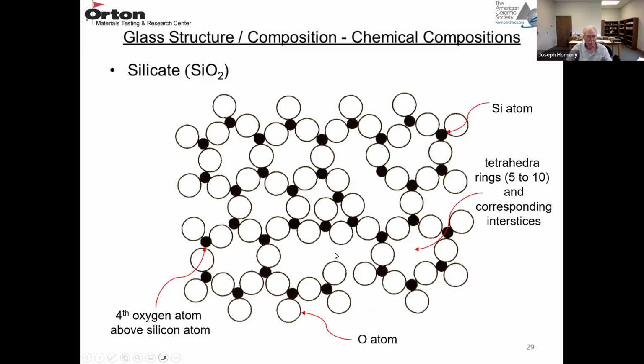So this is a schematic diagram of the silicate glass. The black circles are the Si atoms. The open circles are the oxygen atoms. And here's a silicon atom surrounded by three oxygens. This is just a cut in one plane. So there'd be a fourth oxygen atom sitting above that silicon atom to form the tetrahedron. So they're sharing oxygen atoms at the corners. The structure is random. And you can see when they share, this is a ring here, sharing the corners of the oxygens, they create this open space. So you're forming these tetrahedral rings, maybe 5 to 10, and then you're creating these void spaces. So that's what a pure SiO2 glass would look like.